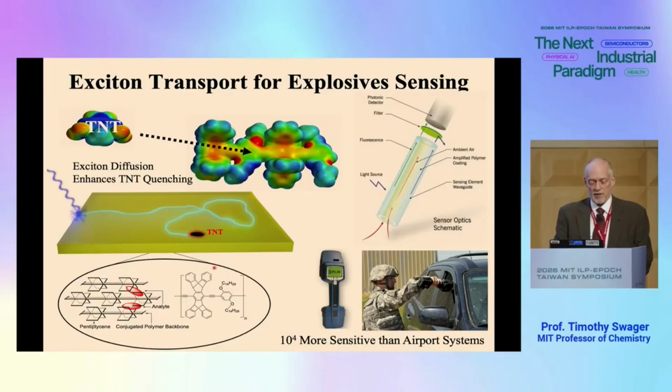In this case, what we did is we just showed that you can make films of a polymer. This is the semiconducting organic polymer. This is the pi system along the backbone here. And it had these little wings on it that create a nanoporous environment that only lets small molecules in and prevents self-quenching of the polymers. It keeps the polymer chains apart a little bit.